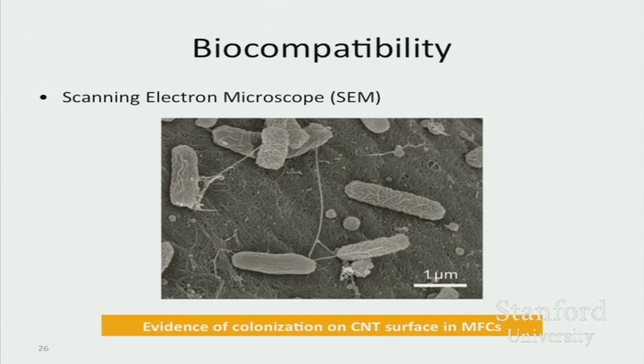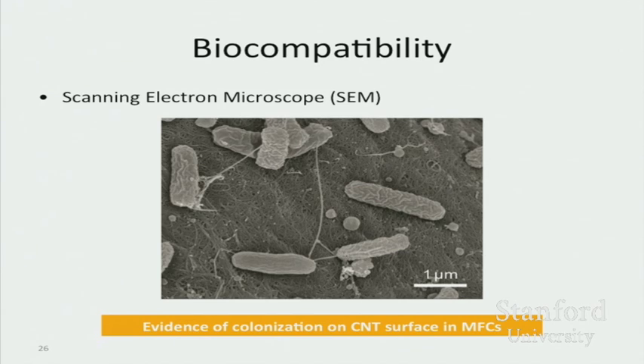The first thing we notice, this is our carbon nanotube textile. You see each of these nanotubes sitting right here, a wire-like structure, right, forming a film, nicely sitting onto the textile fiber. Now each of these rod-shaped structures, this is under a scanning electron microscope, these are those microbes. And they sit very happily. How do I know they're sitting very happily? I'm going to show you the data, because they perform the job. So only happy people can be efficient. So that's the rationale. So you see this bio nanowire growing out, right?